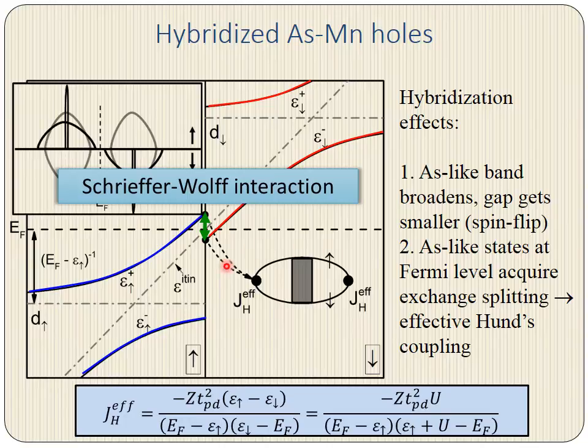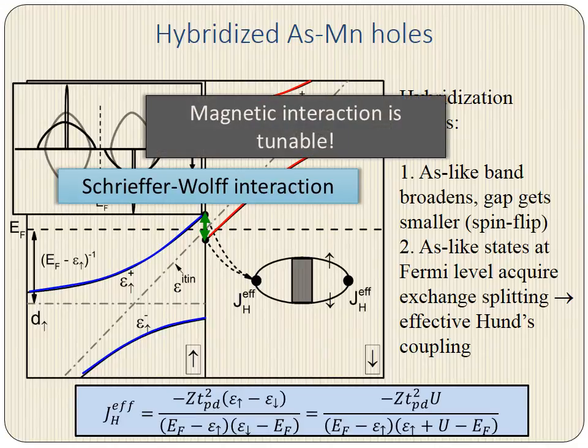So, in the end, since we have the same diagram, everything is squared and minus signs will disappear, we see that we actually have the same effective interaction as the classical double exchange picture. So the ferromagnetic interaction in our system can be viewed as an effective double exchange, in which the coupling at the vertices is a modified expression that depends on the location of our occupied manganese 3D band and the Hubbard U splitting between spin up and spin down. So, in principle, the magnetic interaction is tunable. This, of course, holds promise that the Curie temperature could be driven higher by substituting arsenic with something like antimony or phosphorus, because this might place the occupied manganese 3D band elsewhere. Of course, further work in this direction is needed.